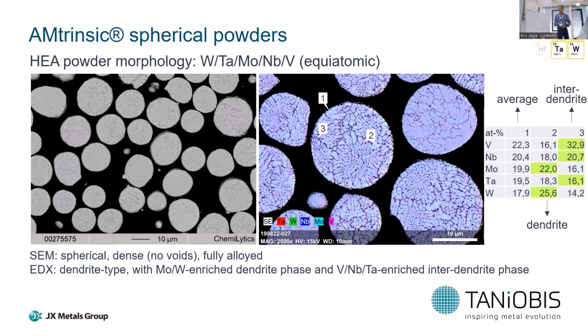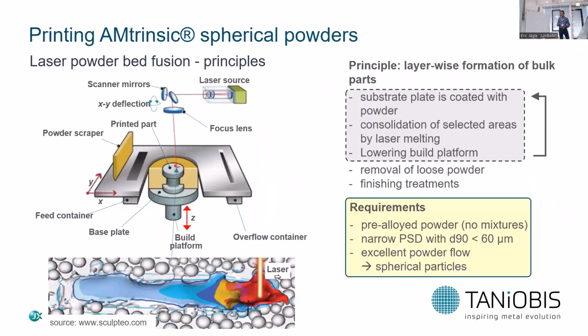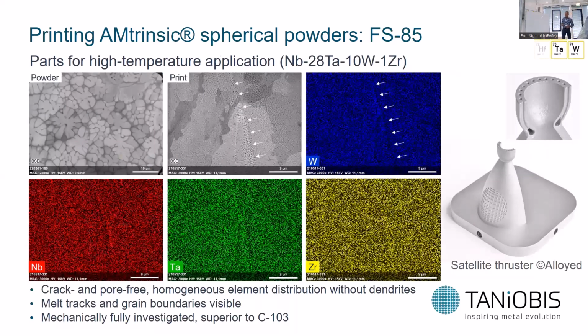Okay, the next step is we go to printed powders. I do not explain this because everyone knows, but I would like to point out the yellow box here. It's very important to have a homogeneous printing process, to deal with pre-alloyed powders, so no powder mixtures, because if you have powder mixtures, usually powders have different density, and when you're recoating the powders, you have a separation of the light from the heavier element powder particles. Very important is also a narrow particle size distribution for laser powder bed fusion, usually below 60 or 63 µm, and an excellent powder flow, which is guaranteed by working with spherical particles.